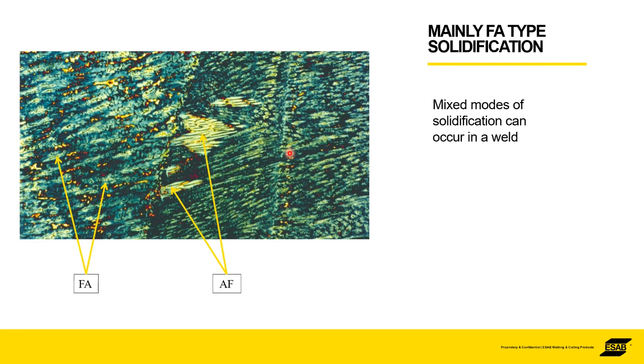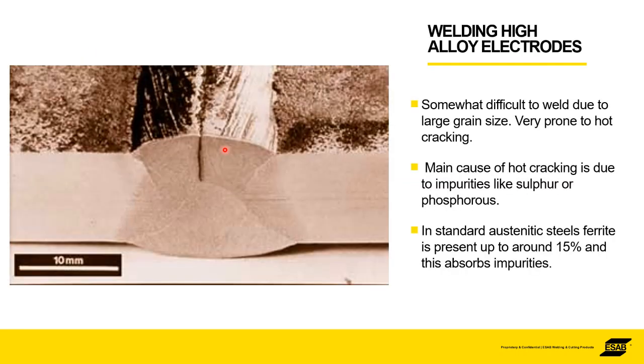Similarly, mixed modes of solidification. Within the same weld, you can get the ferritic solidification mode with austenite in it, or the austenitic mode with a little bit of ferrite in it. So again, these are very highly alloyed materials, and these are the kind of effects that can happen during welding. I'm trying not to get too bogged down.